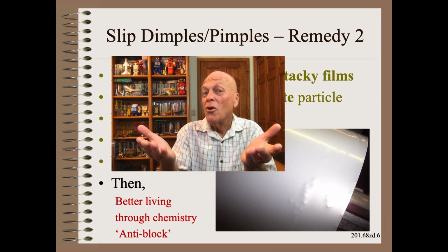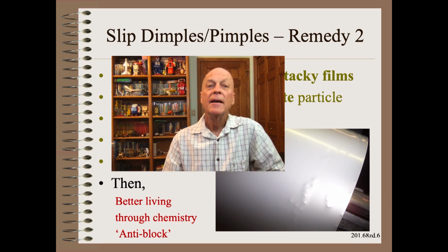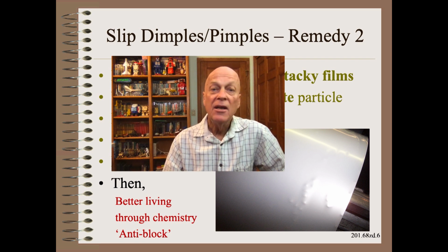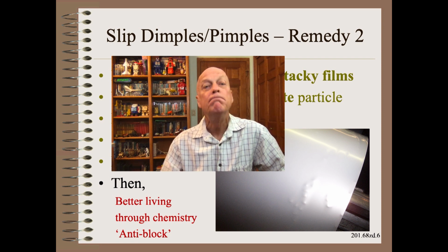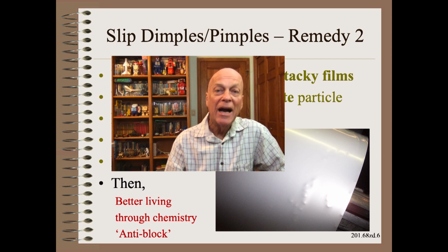You should already be prepared for the more powerful remedy by the grade dependence of this defect. That is, better living through chemistry by adding anti-block or slip agents into the polymer supply prior to extrusion.